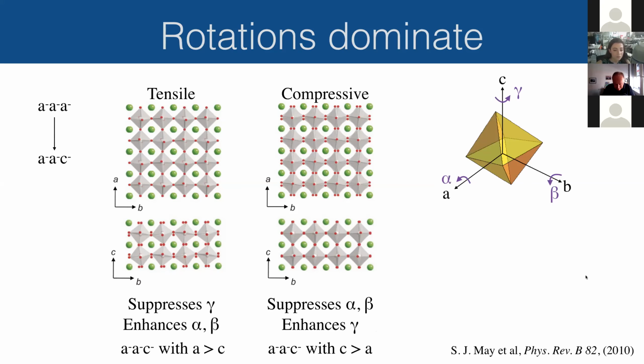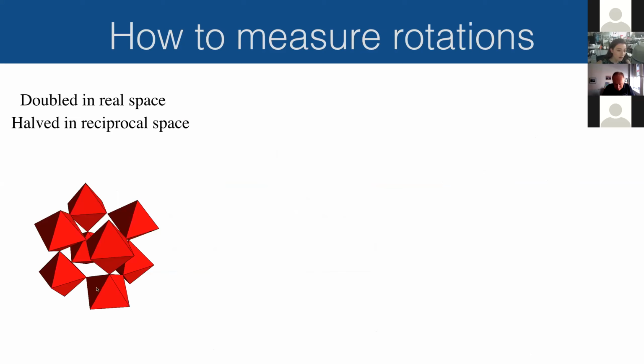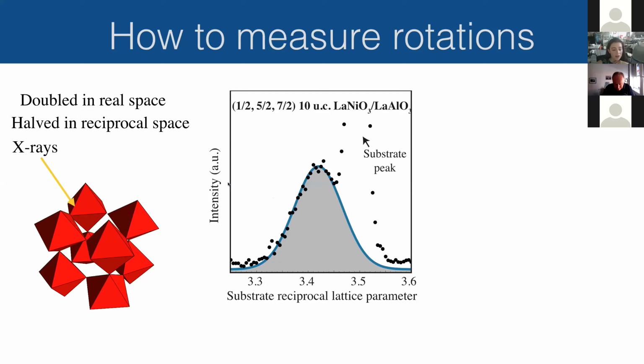I just want to mention very briefly how they achieved this result. So they use the fact that when the perovskite structure is distorted, you have a doubling of the real space unit cells. So now you have to take into account double the number of atoms in one direction to have a periodic repetition. When you double something in real space, you have it halved in reciprocal space. So how do we access reciprocal space? With X-ray diffraction. So you send X-rays in, you measure the diffraction pattern that comes out, and now because you have halved the periodicity in reciprocal space, you have extra peaks at half integers.